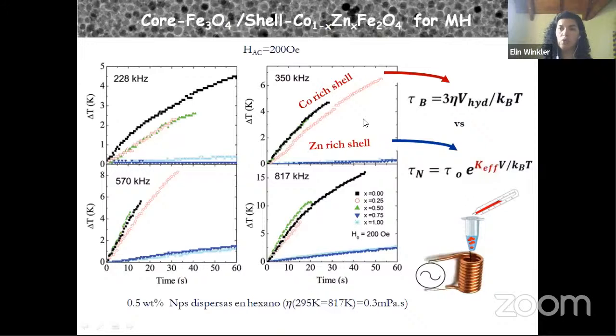But we observe that there are two groups of nanoparticles. There are three systems that produce hyperthermia, and there are two others that do not produce any heating of the medium. So, the nanoparticles that produce a heating of the medium present a lot of cobalt in the shell. Remember that the cobalt is responsible for increasing the magnetic anisotropy. So as these samples have a very large anisotropy, it means they have a very large Néel relaxation time. So these systems will relax by the Brown relaxation. On the contrary, as we reduce this parameter when we replace cobalt by zinc, we think that this system will be relaxed by the Néel relaxation.